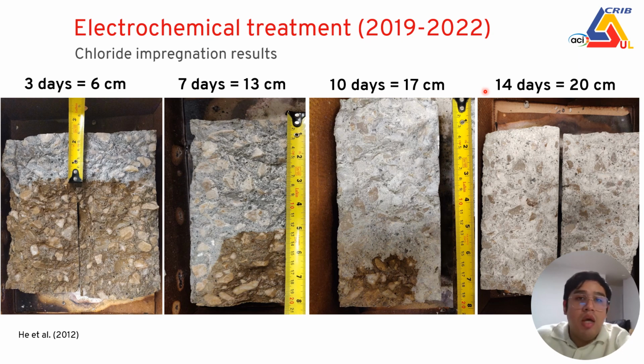And I used a colorimetric measurement by spraying silver nitrate on the concrete specimen. And we can see here in a gray or whitish color the chloride profile advancing inside the concrete.